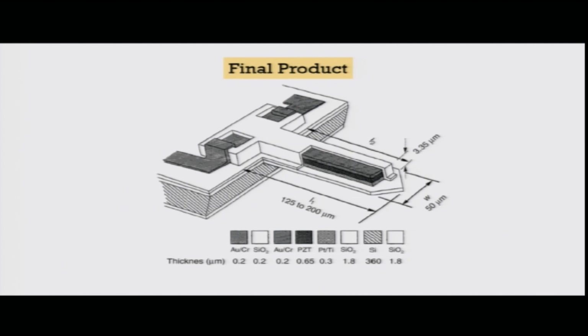So, you can get a final product by using any one of these methods, bulk micromachining or surface micromachining or wet etching, dry etching, you can get this kind of a system. As you can see that this is a cantilever beam here and this can be typically a probe of atomic force microscope and you can see that it has various layers in it if you cut it, and those various layers can be something like gold chromium deposition, silica, gold chromium and PZT, then the platinum titanium silica, etc. So, you can make a functionally graded structure, you can make a smart structure all in micron scale.